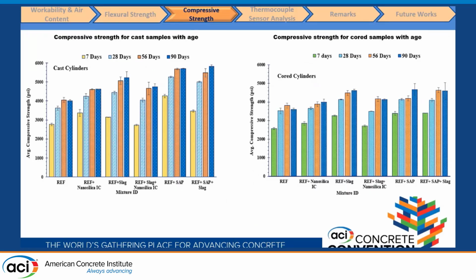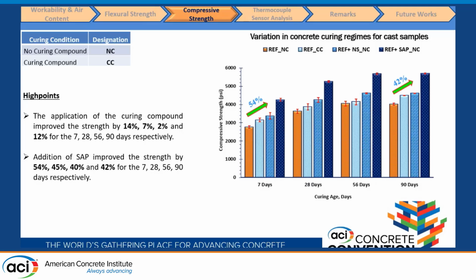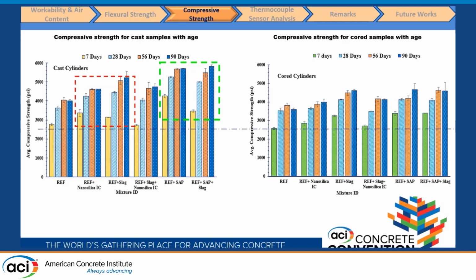Then for compressive strength, the incorporation of the admixtures, superabsorbent, the slag, and nanosilica improved the compressive strength by 14% at 7 days and 30% at 90 days. And also the addition of SAP improved the compressive strength by 54% at 7 days and 42% at 90 days. And the samples from the cores were also extracted from the slabs in the field, and the trend was similar when we tested the cores, just with a slight decrease in the strength.